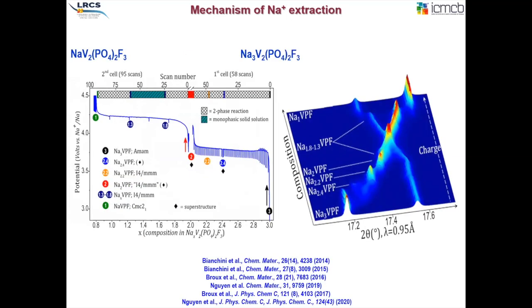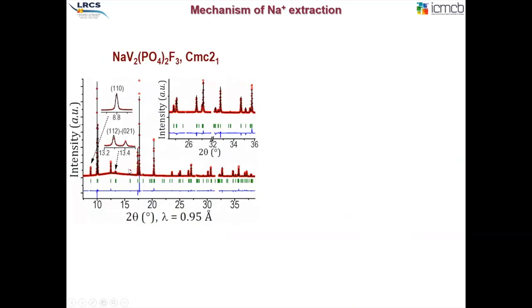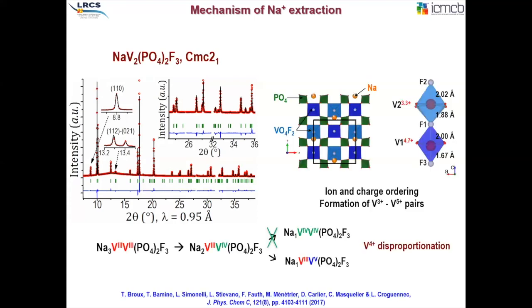When we fully extract sodium from Na3 to Na1 here, we realize that there are some subtle phase transformations that lead to different space groups than the pristine one. And the most interesting feature is that instead of having vanadium 4 plus oxidation state for the given compound, we realize that at the end of charge, for the sodium 1 composition, there is a disproportionation that occurs.